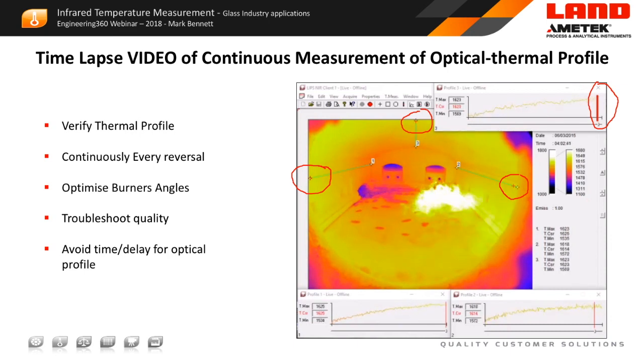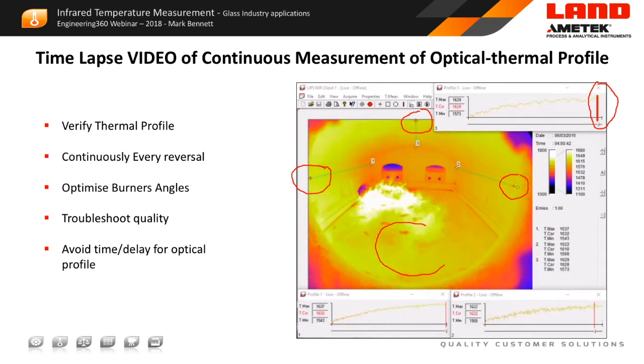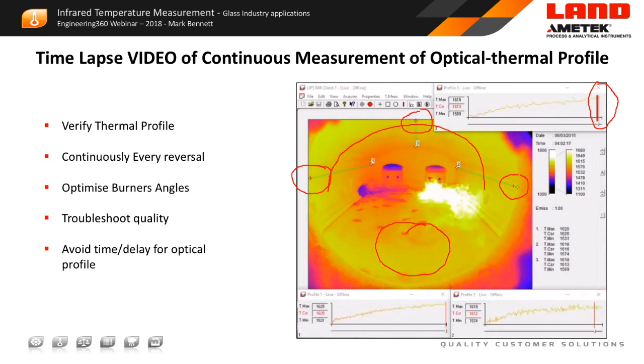So you can see by monitoring the area for high temperatures, you will protect damage occurring to the refractory within the tank. So bear in mind that what we have here is molten glass. So in the bottom of this tank here, we're looking at something which is in the region of maybe 1600 degrees C. The wall temperatures and the crown are heated to maybe 1560, 1600. But the maximum temperature before you cause damage is somewhere around 1620 to 1650 degrees, depending on the type of refractory that's used.